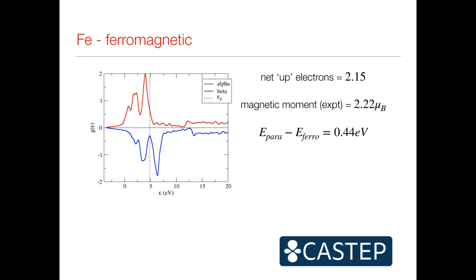You can see a few things here. First of all, the magnetic moment due to the spin of the electron pretty much accounts for the observed magnetic moment in iron. So the magnetism of iron is almost completely, to within a couple of percent, coming from the spin angular momentum of the electrons. The contribution from any orbital motion is actually 1 or 2%. It's really quite small.